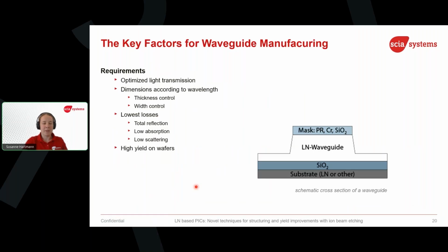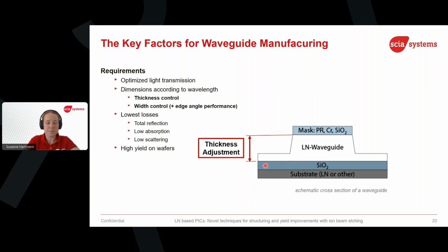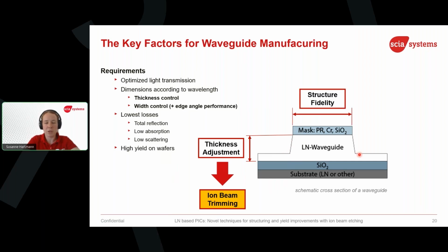Let's step one step back. How do we get such waveguides? For optimized light transmission, we not only need smooth sidewalls, but we need an optimized dimension according to the wavelengths of your application. This means that we need a thickness control of the layer of our lithium niobate, which can be done via ion beam trimming. And we need the width control of our structure from the mask into the lithium niobate. So the structure fidelity is important, which can be done with ion beam etching. Let's first step into the ion beam trimming.